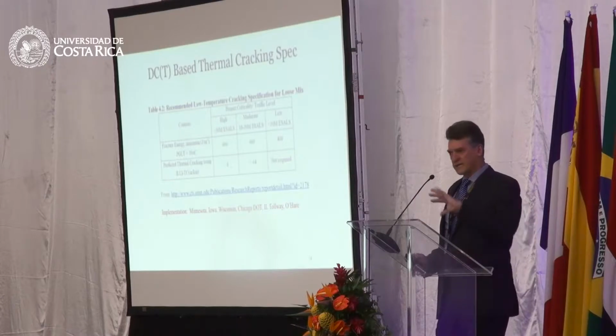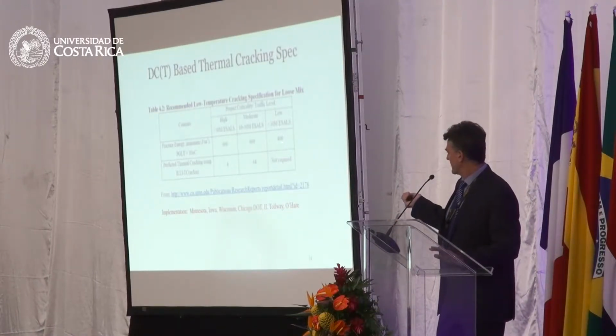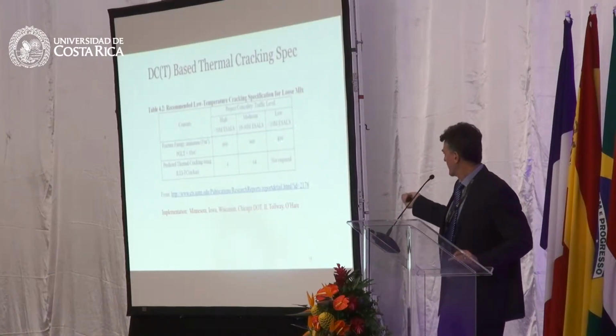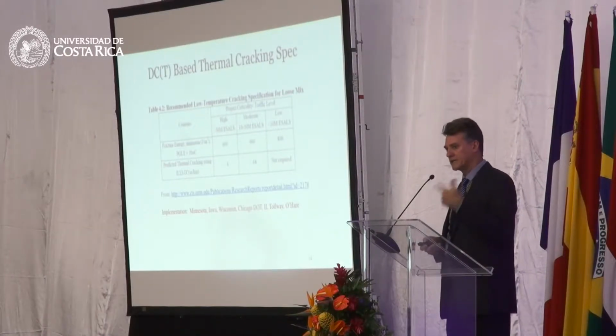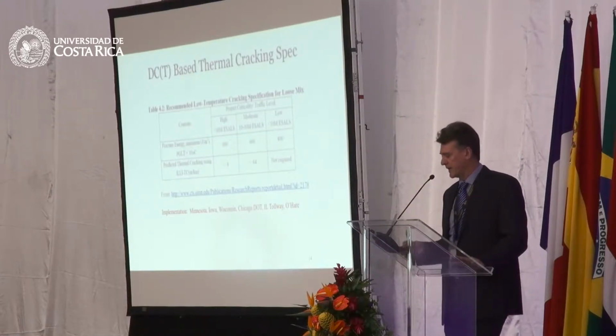The specification we've been using, modified in different states around the United States, in general you're looking for about a 400 joule per meter squared fracture energy for low volume roads. As you get to more important projects where cracking is to be less tolerated, you can use a more conservative value of around 500 or 600 joules per meter squared.